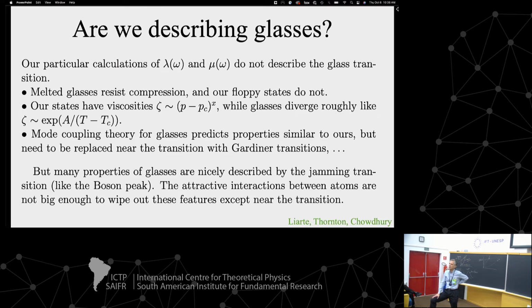But then you can put a lens, and rescale everything with the root of the volume. And then you can look at the rescaled fluctuations. And when you hit this Gardner point, you start to see that these fluctuations diverge. And what does it mean? It means that if you look at the fine structure of the elastic moduli, you start to see avalanches. The divergence of the fluctuations of elastic moduli is just a sign of avalanches. If you take a very big piece of glass, the fluctuations of these things and avalanches are suppressed like 1 over some power of the volume. But if you look a bit more carefully, you can. That's very interesting.